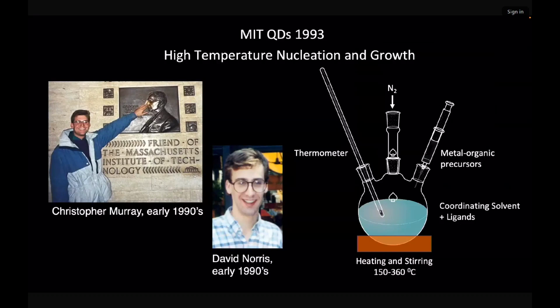And so this is Chris as a young man, and this is David Norris as a young man. And Chris came up with this idea of this high temperature, what is now called the hot injection system. So the precursors are here, and I had learned about some of these precursors from Mike Steigerwald, dimethyl cadmium, a terrible precursor that today we no longer use, but we were a little ignorant at the time. And then a hot solvent, so you take room temperature stable precursors, you inject them into a hot solvent, they crack, they release the atoms that are going to make your quantum dot. And that's the nucleation part.